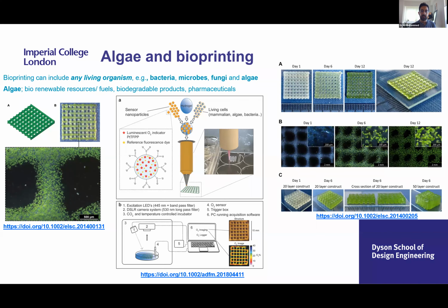And finally, we have a look at another study, which uses an alginate-based hydrogel, and it studies the chlorophyll content and the photosynthetic rates of microalgae printed in a grid-like structure under constant illumination. Again, the 3D print was limited to a basic grid structure that is a few millimeters high. So as you go through the research and find bioprinting with algae or other microorganisms, you find that the main limitation is the design complexity and the ability to print very complex structures.